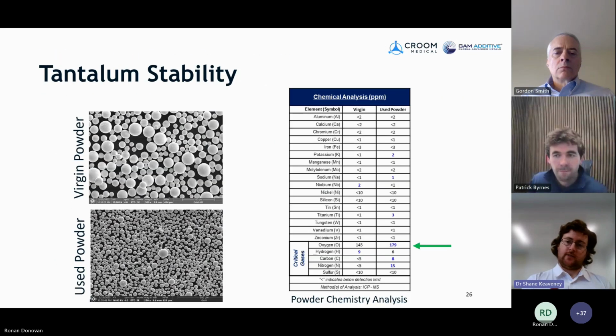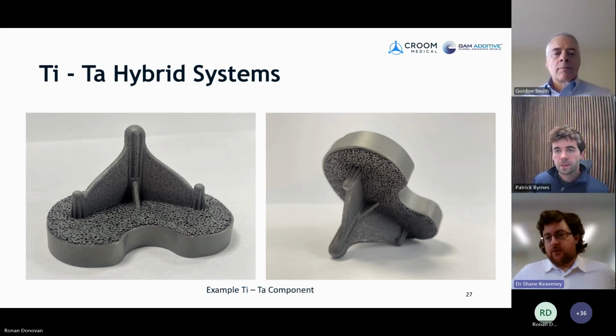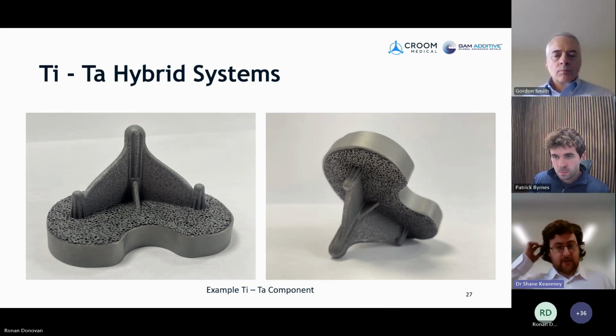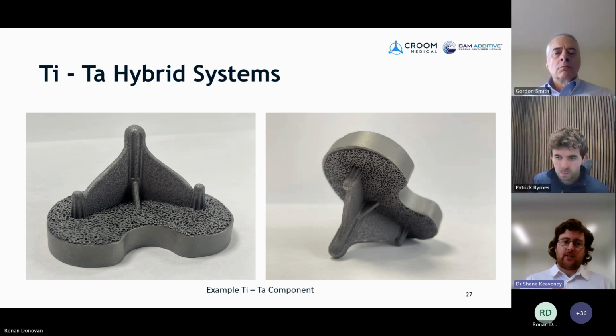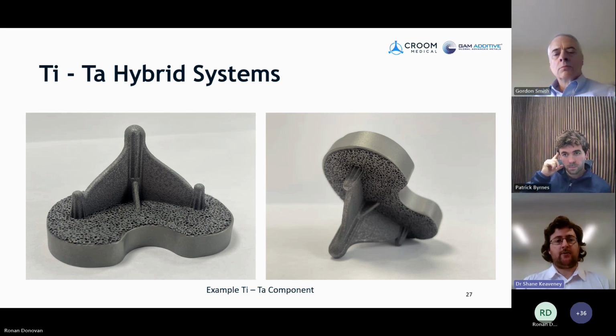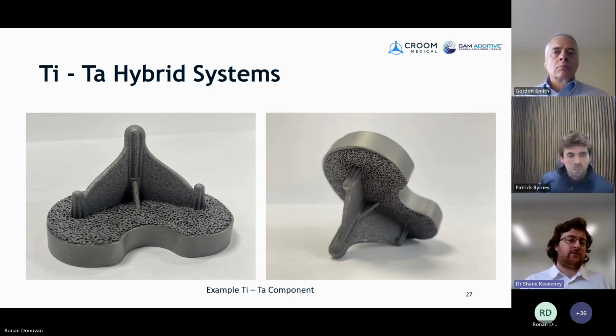Yeah, this is sort of what we're working on here, so we've also recognized that. As you said, it's around 4 times more dense than titanium. But looking at the combination of titanium and tantalum is quite a good approach. The porous tantalum really has good potential benefits, as we said. So in this TaTi hybrid system, the bulk of the structure on the base is titanium, and then the keel and the pore structure is tantalum. What that means is that the density issue is negated. And that's what we're going to investigate further as well.